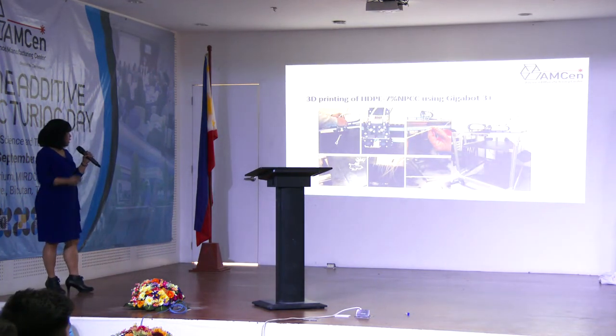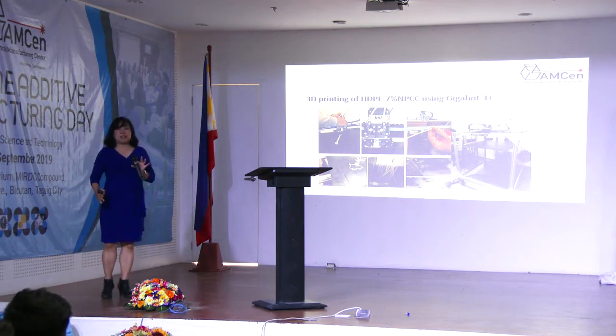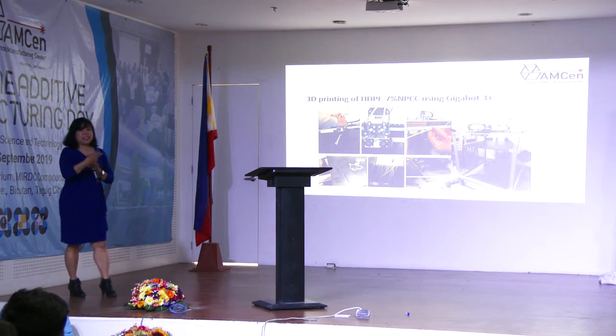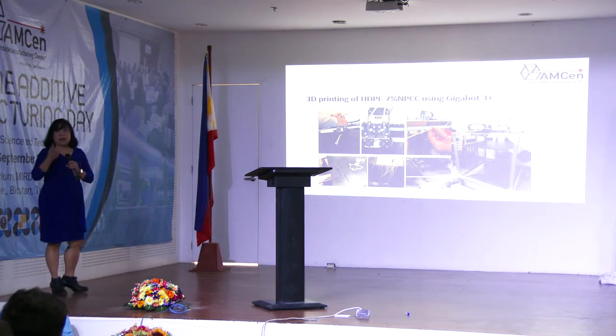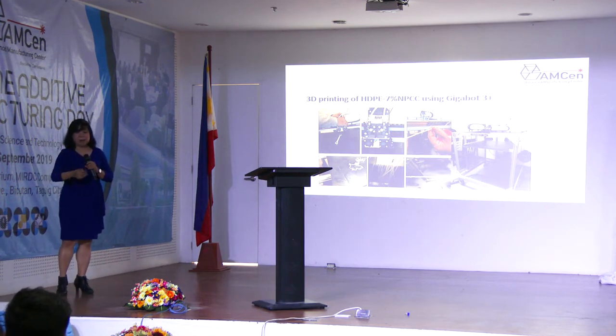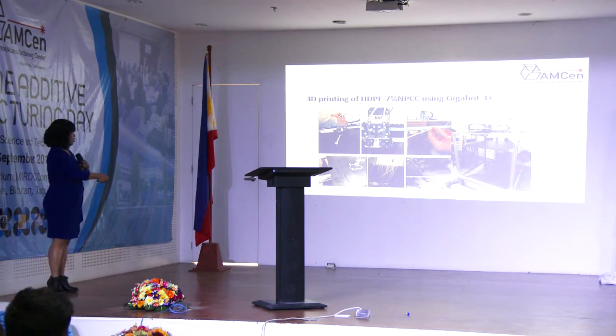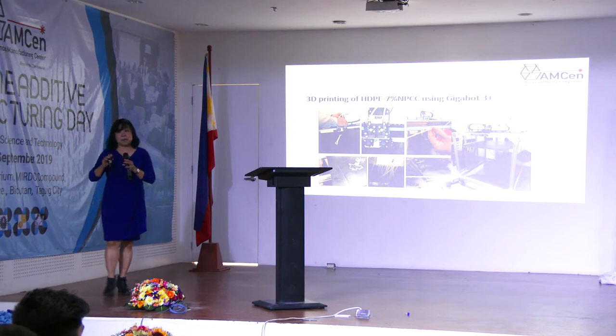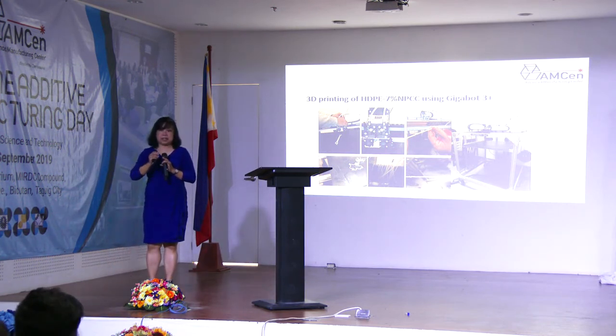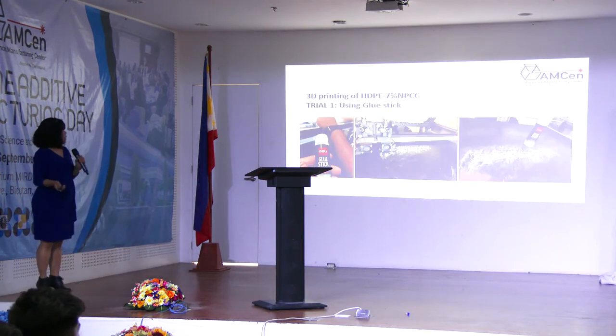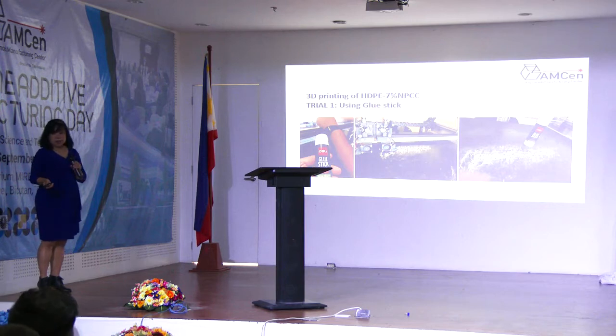Okay, so we use Gigabot 3. This is a type of printer wherein you can print large structures, 1 by 1 by 1 cubic meter of print. Okay, so this is an FDM, and we try to print our nanocomposite. So if you don't optimize the parameters, you can get this type of print. But when we try to operate the printer, we obtain this type of result. The extruded filament did not stick on the metal build plate. So we were not successful in printing 7% nano-precipitated calcium carbonate nanocomposite in HDPE matrix.